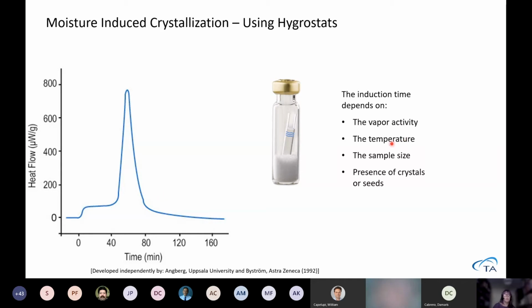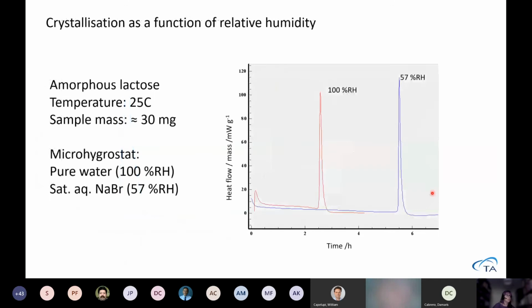The temperature, sample size, and the presence of crystals or seeds also matter. Can you just show an example of how the vapor activity matters? If you have 100% relative humidity, the peaks come quicker than if you have a lower humidity. So depending on whether you have pure water or sodium bromide, that will create this relative humidity. Sample size here is about 30 milligrams, so you don't need to use very much sample, and the sample temperature was 25 degrees.